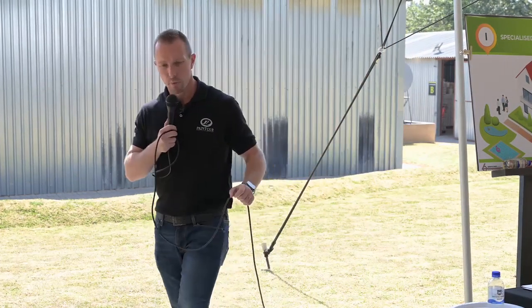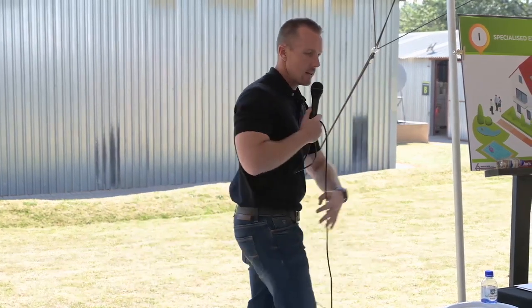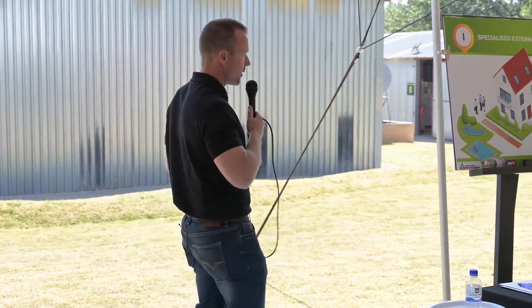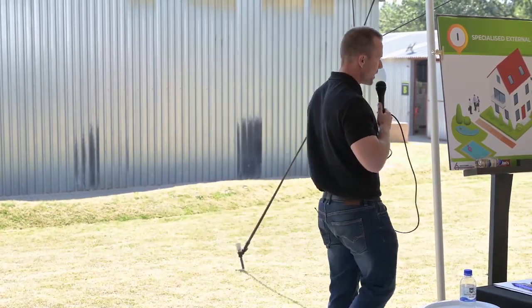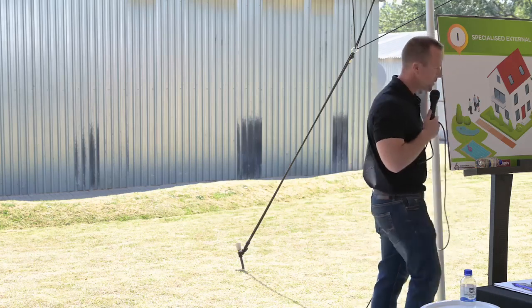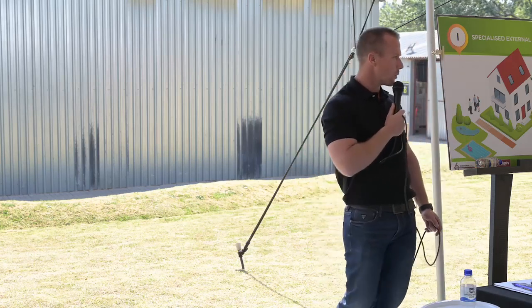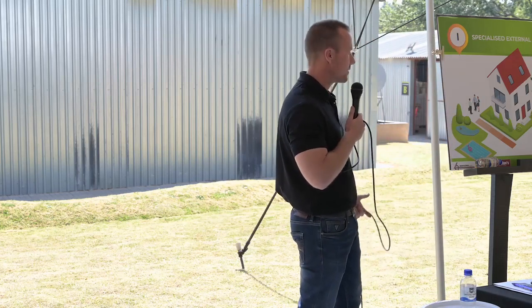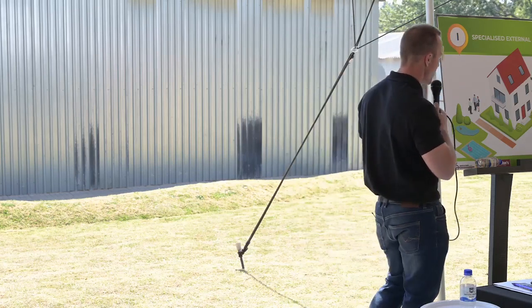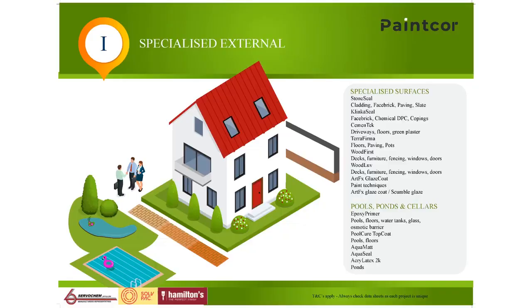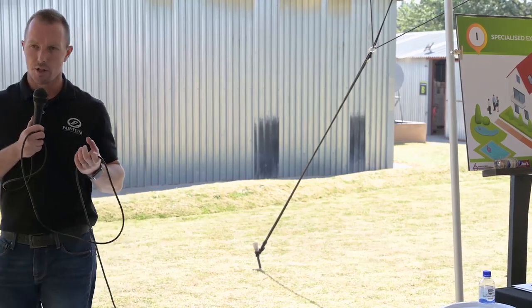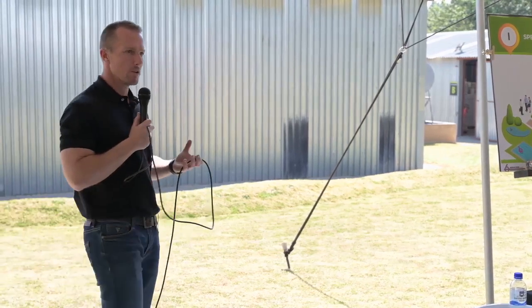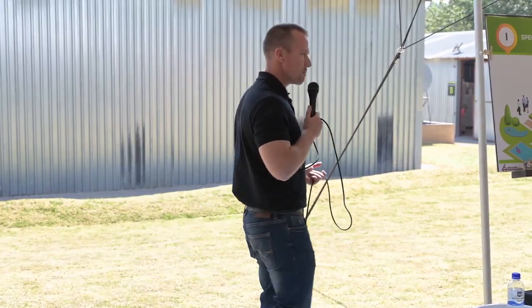I've been to sites where you have gurneys being rolled along walls to flood these bricks with the liquid silicone, the siloxane silicone, and it is hugely effective and will literally stop damp rising through your walls where a DPC should be in place and isn't. So that's the clinker seal, very, very versatile. In fact, the first 3 products on this list, your stone seal, clinker seal and Cementec, are all fairly similar in that the material type used to make them is all silicone based.